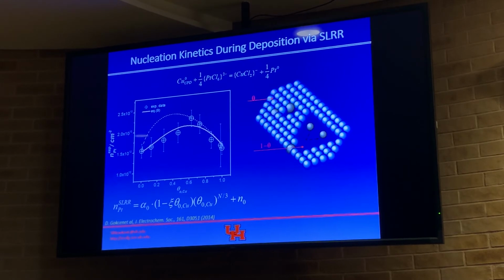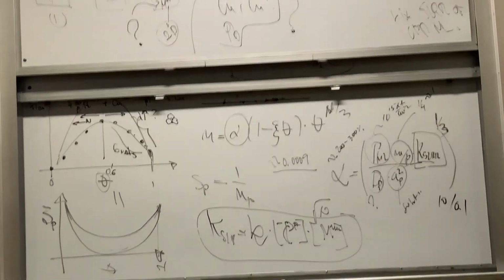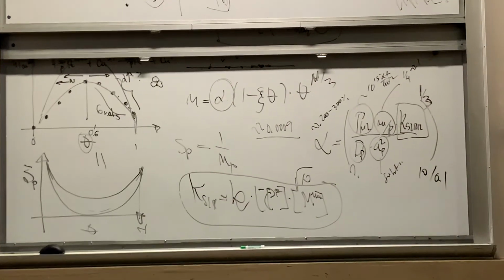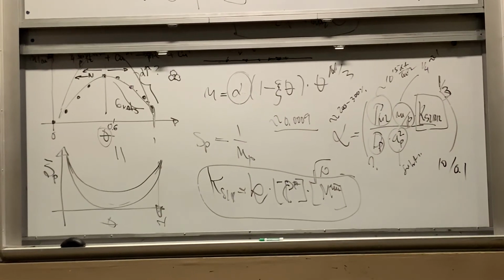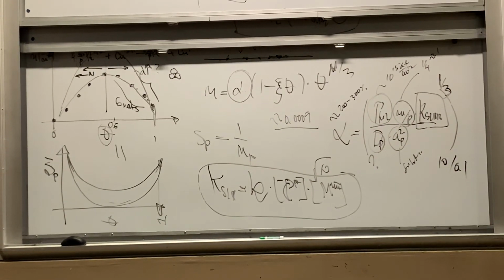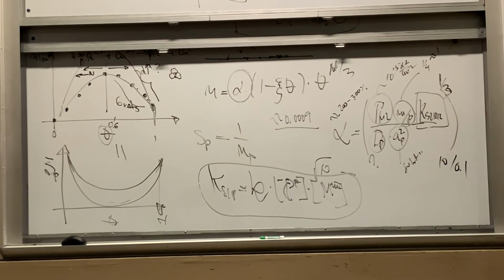It's hard to prove, but some friends of mine did Monte Carlo simulation, and the only way they could get the result in a Monte Carlo simulation is either to model this with a dimer, or to simply put the diffusivity 3 or 4 orders of magnitude higher. So I was lucky a little bit, but I was also right about doing it. And we got to the deposition of platinum.